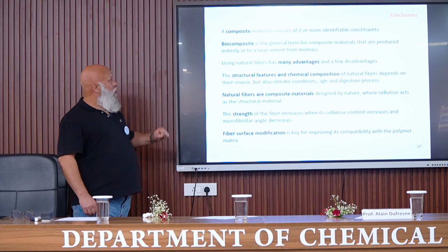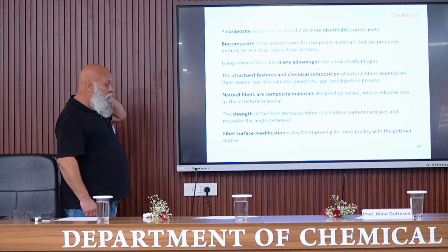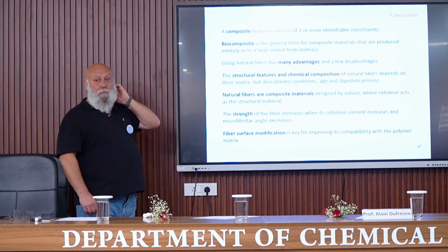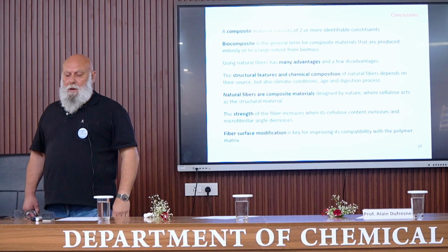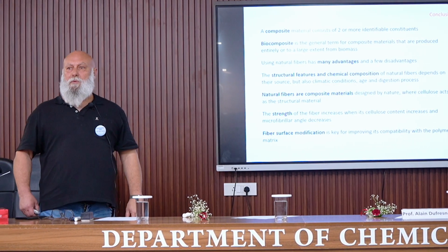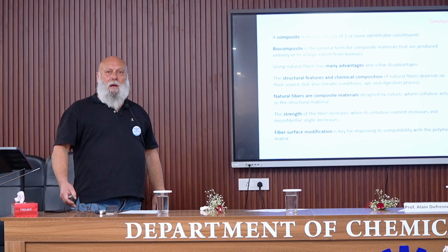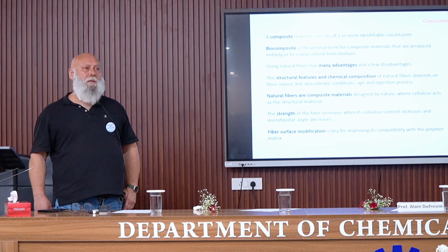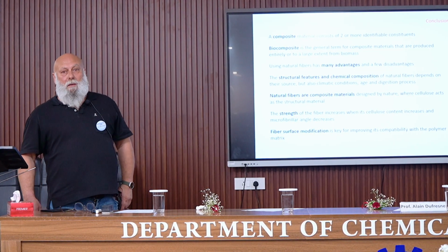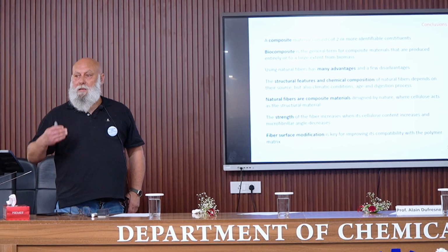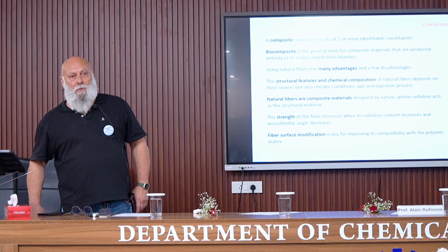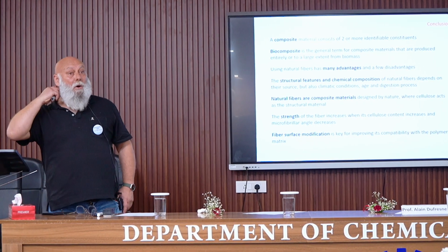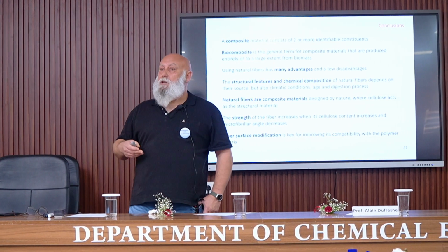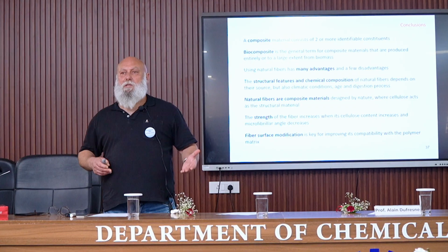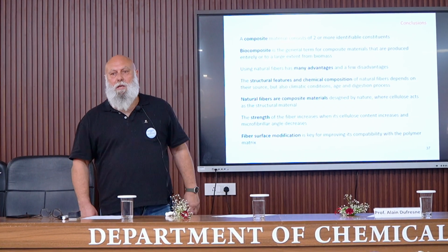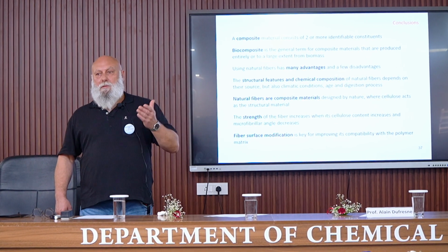And as we mentioned earlier, fiber surface modification is key for improving the compatibility of these natural fibers with the polymer matrix, which is usually hydrophobic. So of course we can find some hydrophilic polymers like polyamides, but there is a difficulty with polyamides. The melting point is very high, so it means that it cannot be blended at high temperature with natural fibers. But of course, we can think about other natural matrices, like starch, for example, that can be used. And because this matrix is hydrophilic, it's usually not necessary to compatibilize the fiber with the matrix.